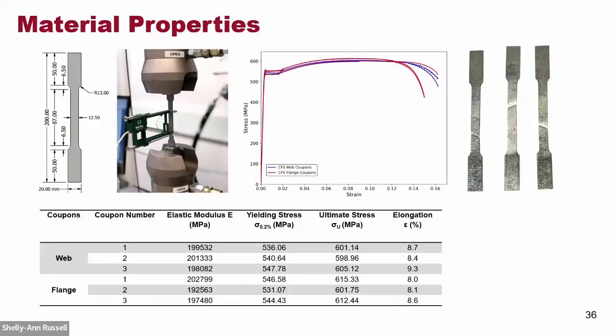We tested these materials under tensile load. We cut coupons, 3 from the web and 3 from the flange. And we found that it is a high strength material. By the offset method, the yield stress is 540 MPa on average, and the elastic modulus is nearly 200,000 MPa. And around 600 MPa is the ultimate stress. You can see the stress-strain curves, and the strain was recorded with this extensometer, and also you can see the coupon failures.